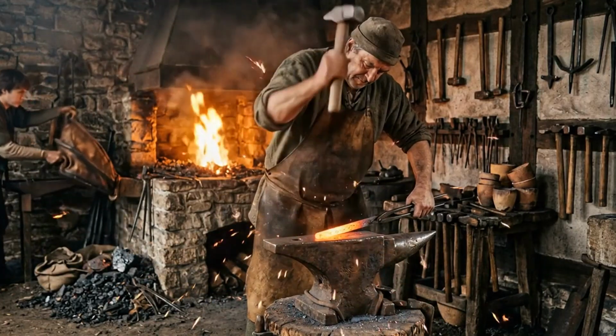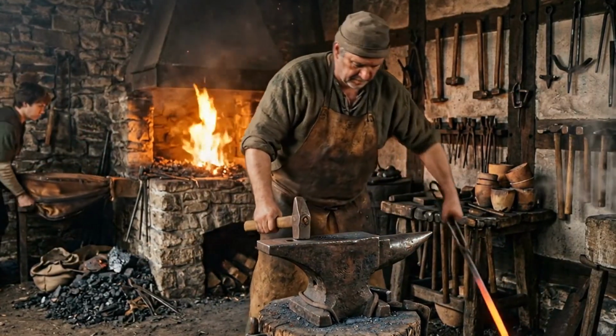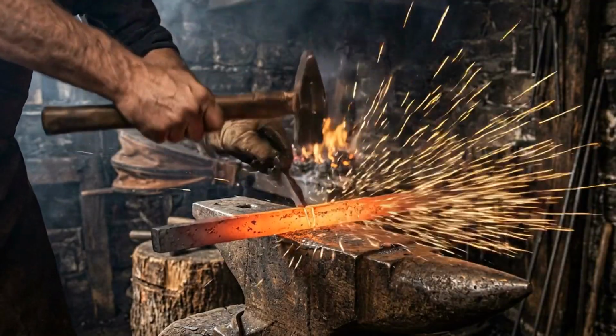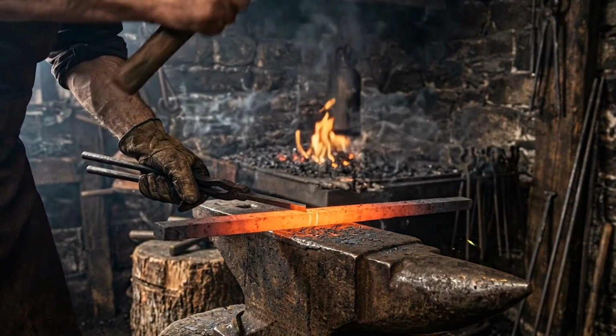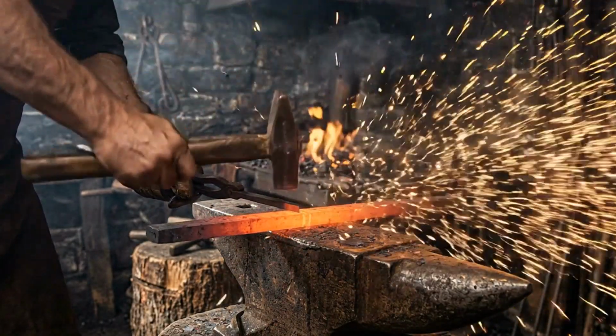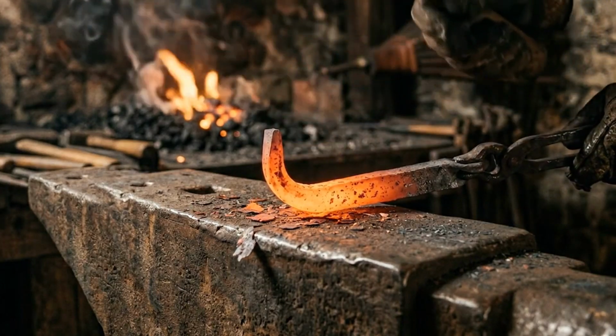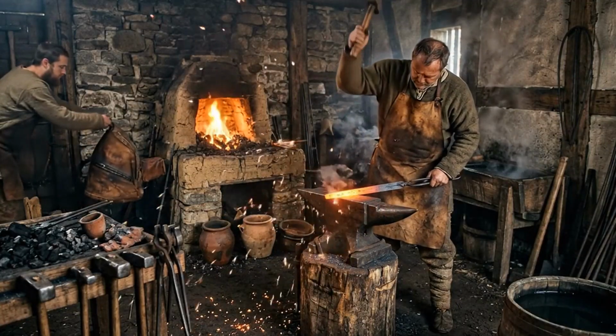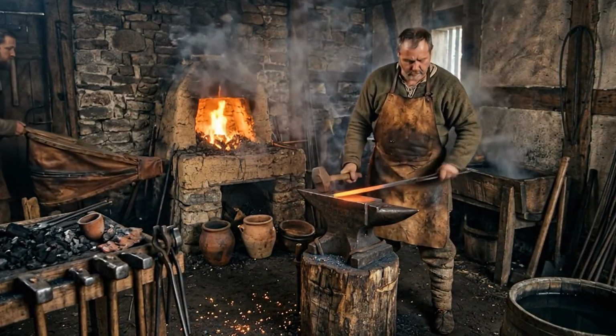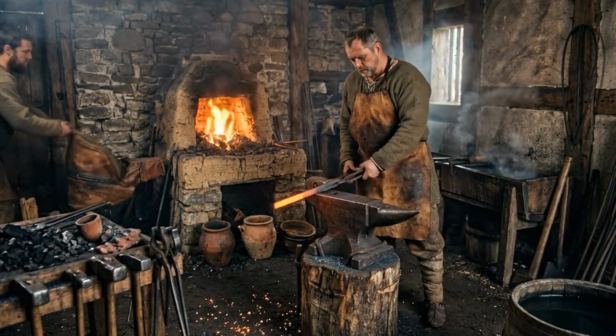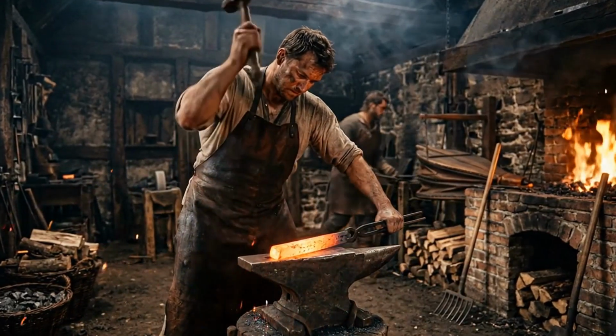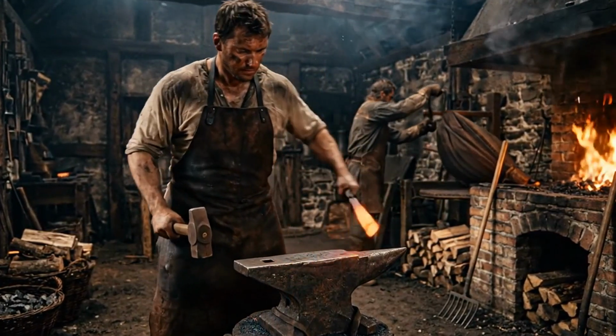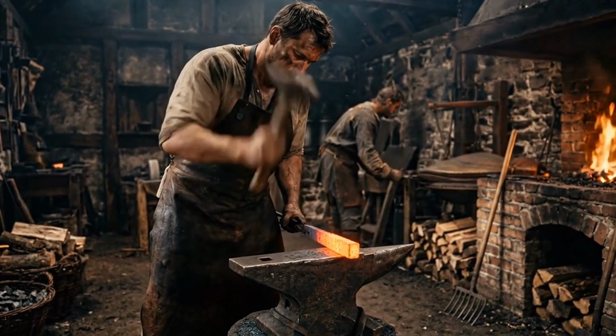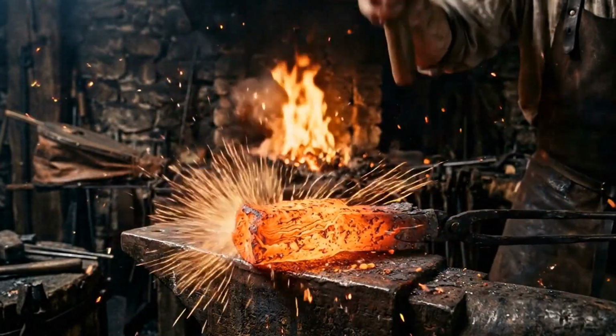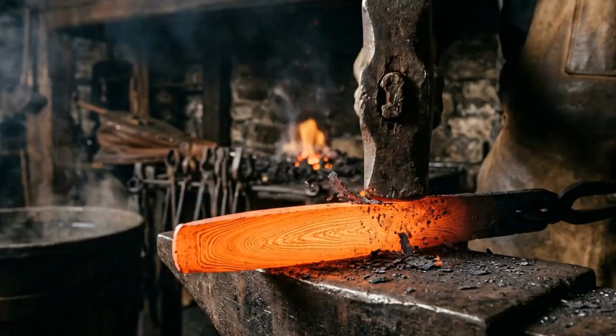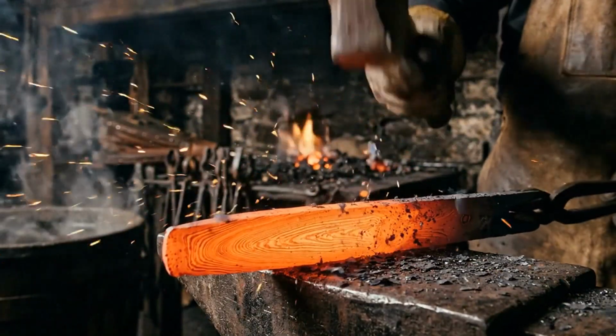Once consolidated, the steel mass was drawn out into a flat bar and folded. This folding process, called orikaeshi tanren, was the defining technique of Japanese swordsmithing and the source of the katana's characteristic internal structure. The bar was heated, hammered flat, scored along its length with a chisel, and folded back on itself. Then it was welded shut by hammer blows and drawn out again. Each fold doubled the number of layers within the steel. After 10 folds, the bar contained more than 1,000 distinct layers. After 15 folds, the number exceeded 30,000.